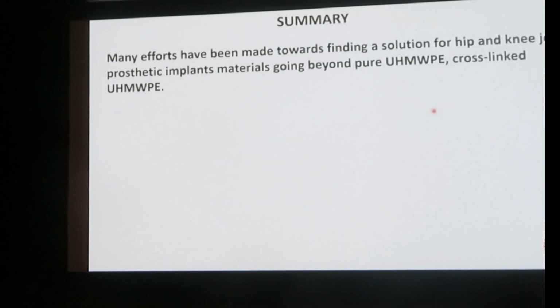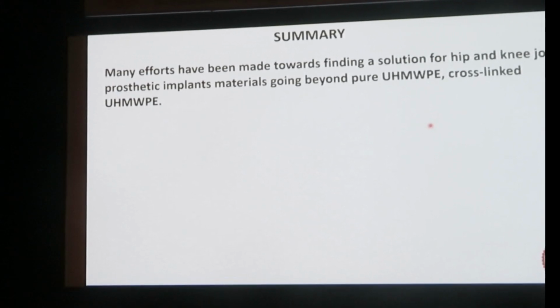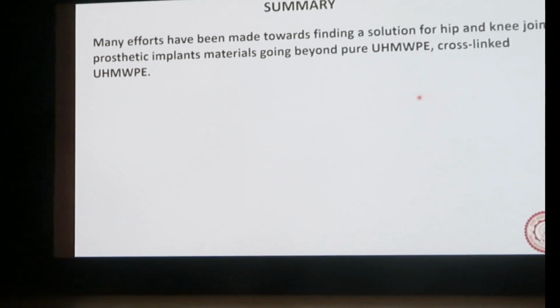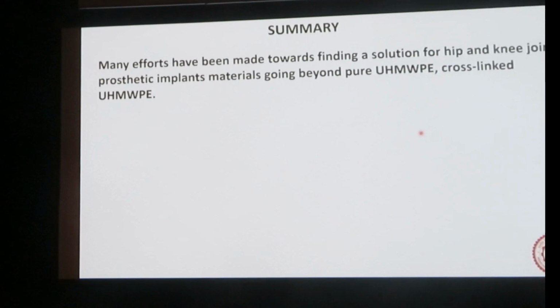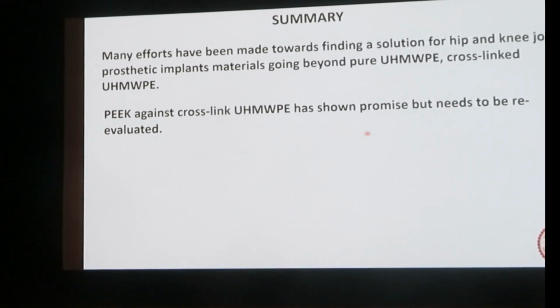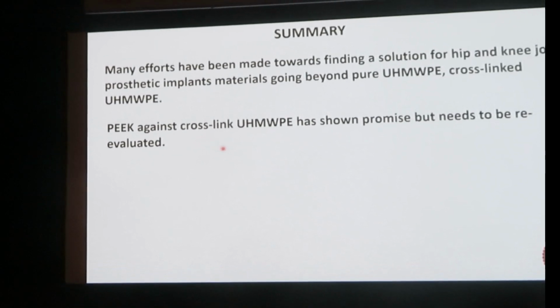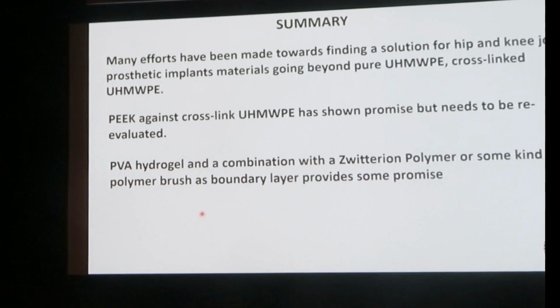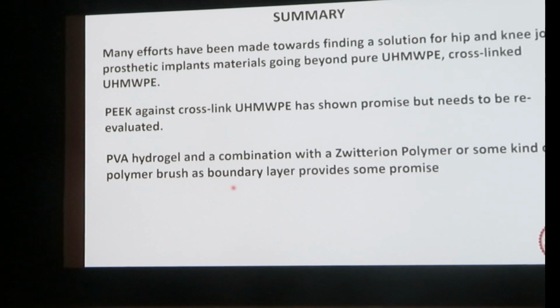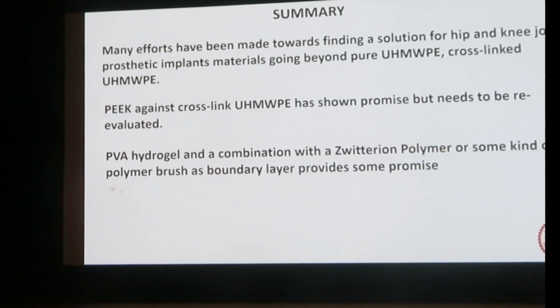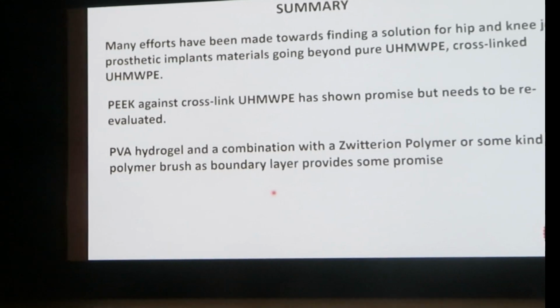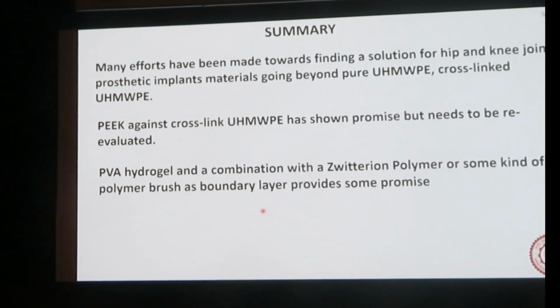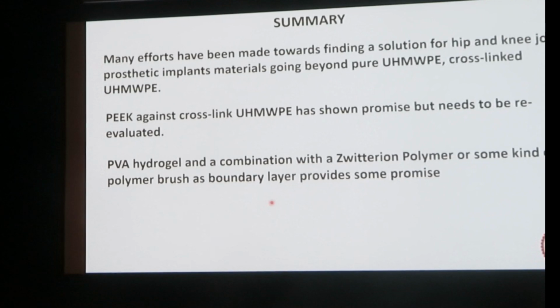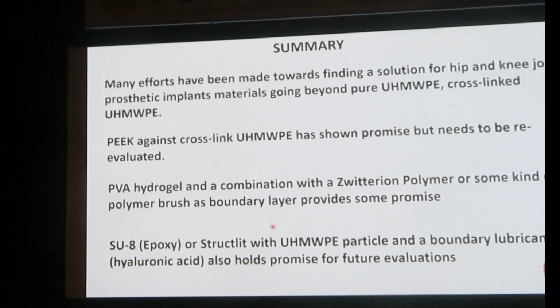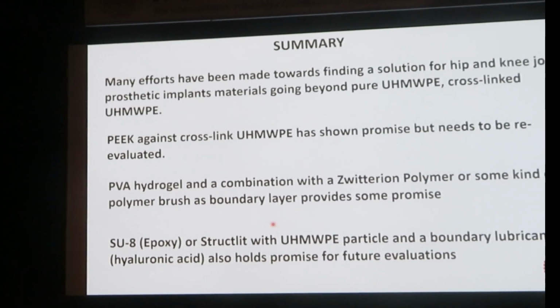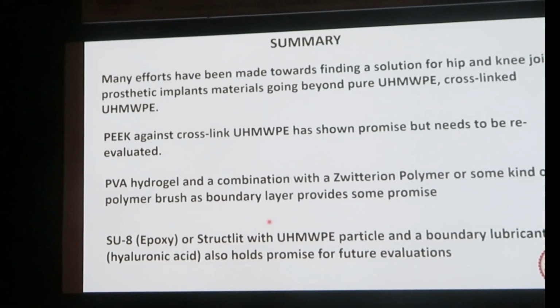So I would like to summarize. Many efforts have been made towards finding a solution for hip and knee joint prosthetic implant materials, going beyond pure UHMWPE or cross-linked UHMWPE or even with vitamin E. PEEK against cross-linked UHMWPE has shown promise but needs to be re-evaluated. PVA hydrogel in combination with a zwitterionic polymer or some kind of polymer brush as a boundary layer provides some promise. As we improve the mechanical property of the hydrogel and add some boundary lubricant on the top surface, perhaps that will mimic the actual cartilage. And epoxy, the SU8 and Structolite with UHMWPE particles and the body lubrication of HA, hyaluronic acid, can also hold some promise in the future.